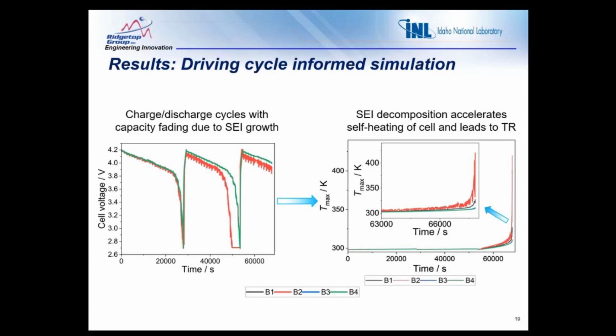These results highlight the non-uniform degradation and thermal behavior among cells, emphasizing the need for monitoring and balancing mechanisms in battery packs, and also the crucial role of SEI decomposition in triggering thermal runaway, especially under realistic driving conditions.